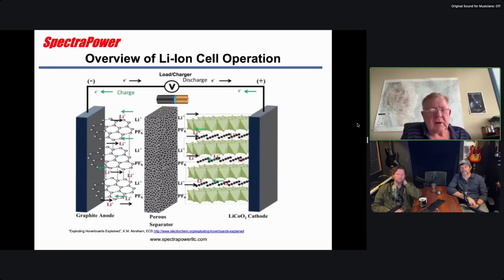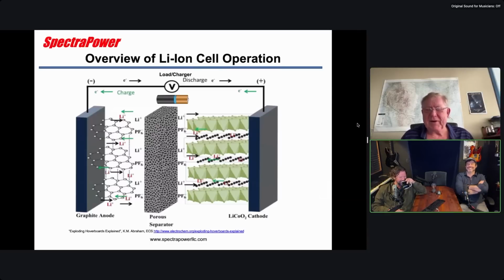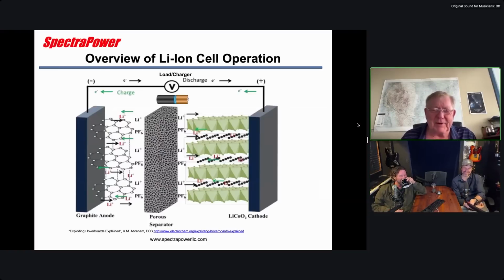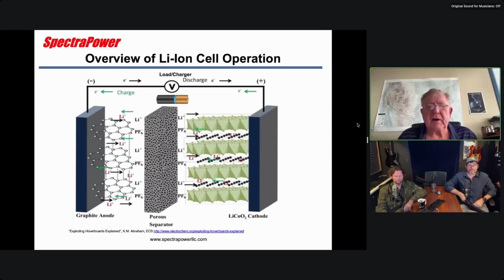The other thing that is a common problem is low temperature operation. This electrolyte is just like the oil in your engine: when it gets really cold, the oil gets very viscous and sluggish, right? When you try to crank it, it's rrr. You guys in Texas don't have that problem, but there are people that do, especially EVs in cold climates. And you don't want to try and charge a lithium-ion cell when it's really cold, like 0 or 10 degrees Fahrenheit. Especially when it gets real cold, this electrolyte can actually freeze. But at the very least, it becomes very viscous and thick, and the ions don't move through it well.